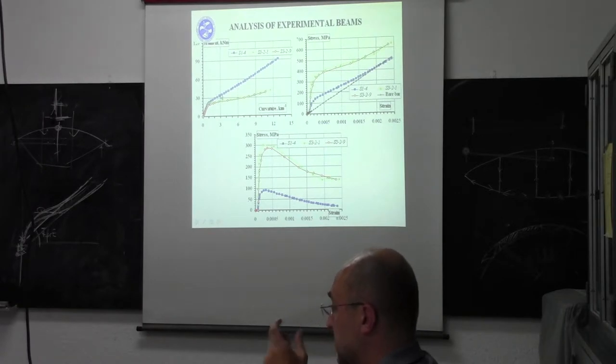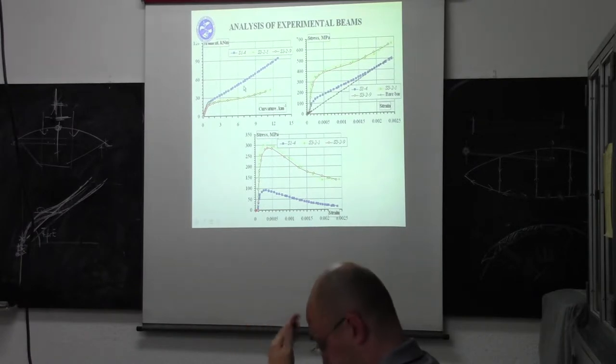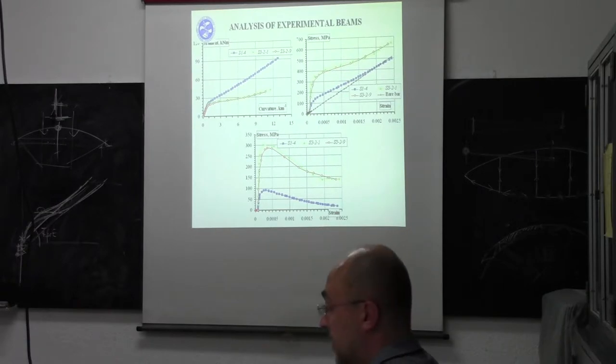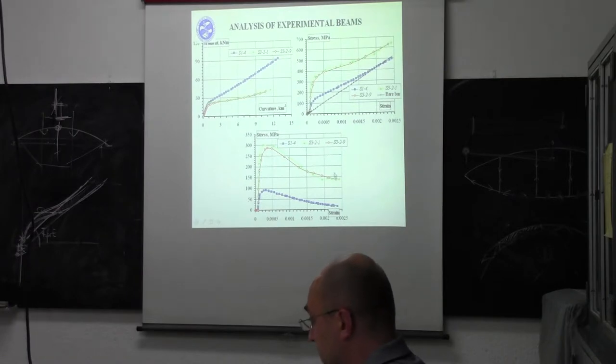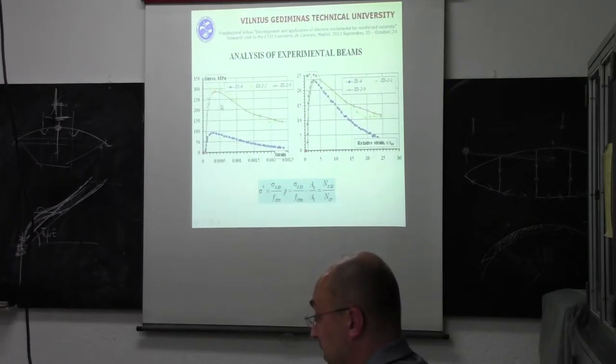We eliminate the shrinkage effect and obtain these diagrams in respect to steel. Then, considering only the portion of tension stiffening in these diagrams, we can compare these diagrams. As we can see, the tension stiffening stress in the beams with high reinforcement was high, but if we explain these diagrams,